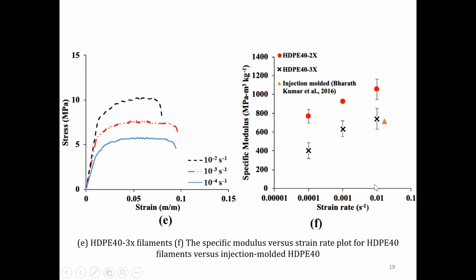Now, as you saw, for a given strain rate, okay, strain rate is the rate of loading in tension, the 3 times extruded filament is performing much better than the completely dense dog bone sample. The 2 times extruded is outperforming the injection molded sample. So as filaments are outperforming the completely dense injection molded sample, there is definitely a sense in jumping into 3D printing and dedicating some time for 3D printing of these compositions.